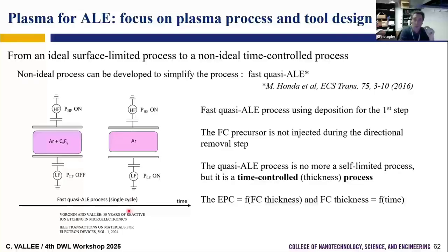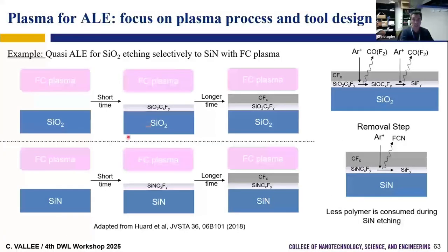So it means that, in fact, we don't have a self-limited process, because if we increase the time of this step, we increase the thickness of the fluorocarbon layer. It's not self-limited. So it's more a time control process, a thickness control process. So you have to optimize this step to optimize the thickness of the fluorocarbon, to be able after to do your etching process through the fluorocarbon layer like any RIE. And so the etch per cycle will depend on the fluorocarbon thickness you deposit in the first step. And the thickness you deposit will depend on the time of the first step. So it's a time control ALE process, not a self-limited ALE process. This is quasi-ALE.